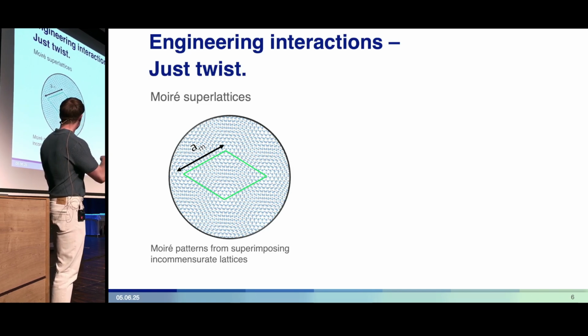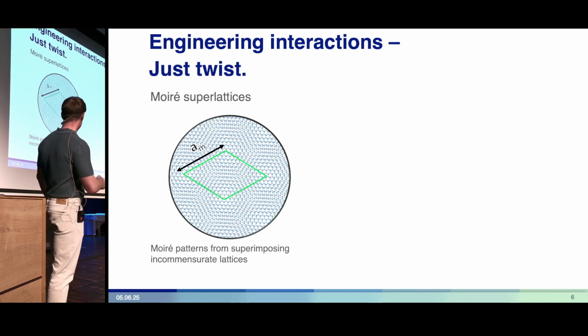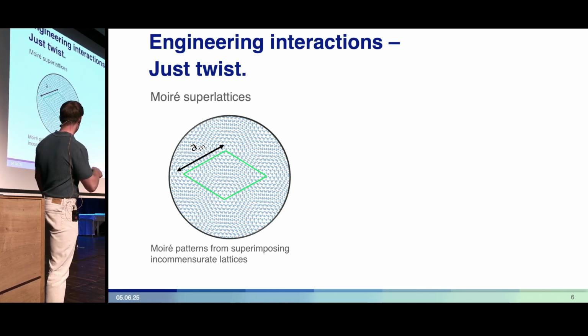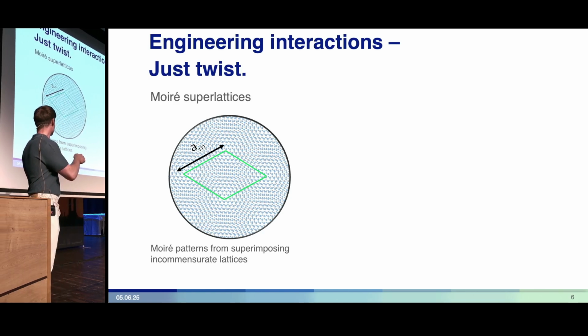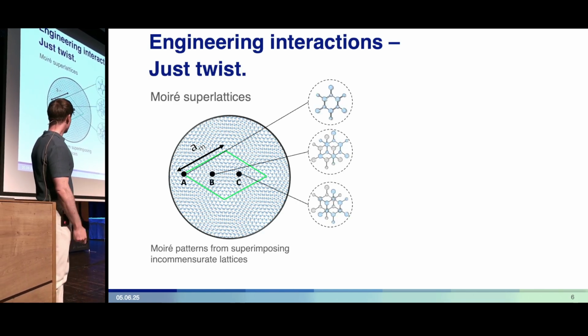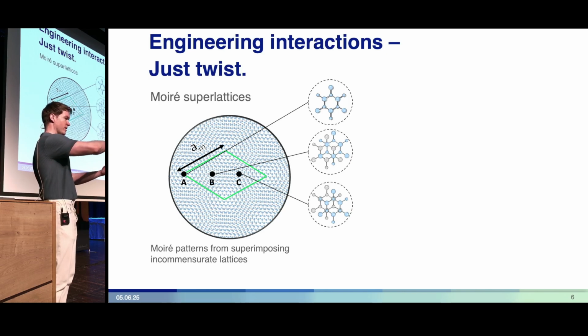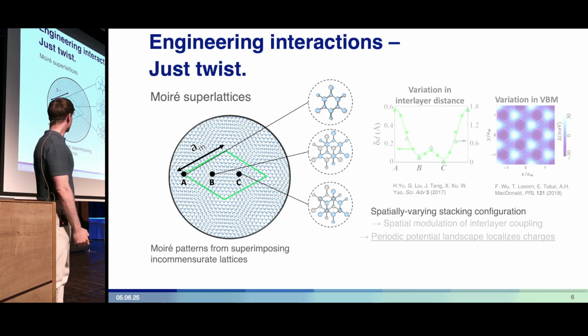And you can see here I've drawn a new unit cell, and the individual unit cells of the sublattices are quite small, about this big, and I have a new unit cell in my Moiré pattern, which is much bigger, a new periodicity, a Moiré. Across the Moiré unit cell, you can see that I realize different stacking orders. They correspond to different registries between atoms in adjacent layers.